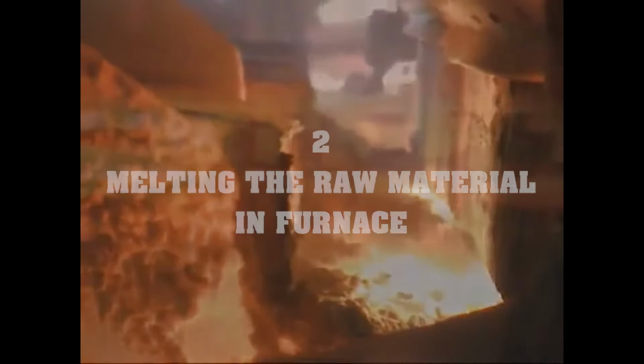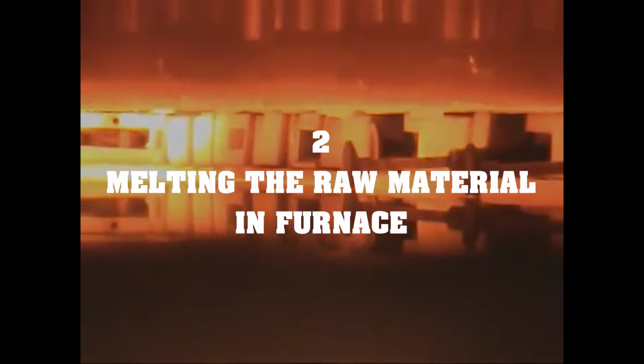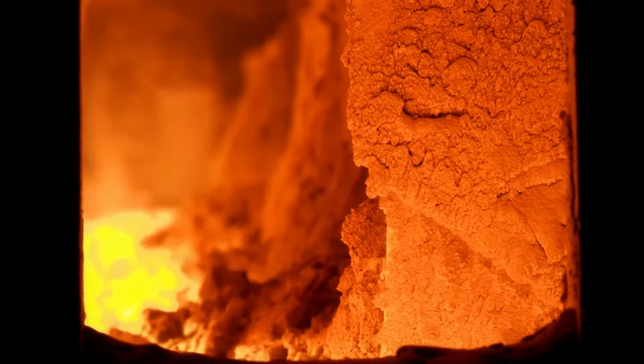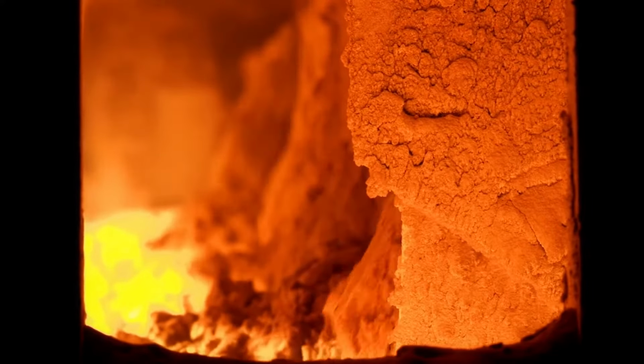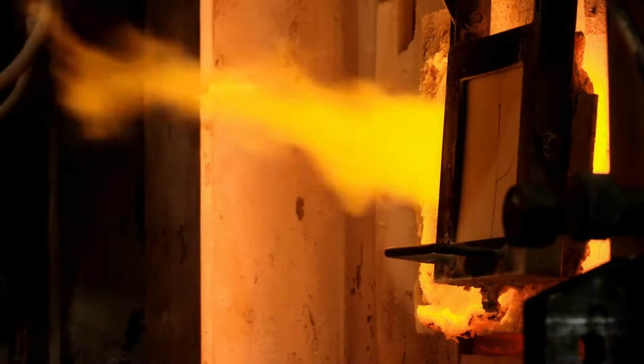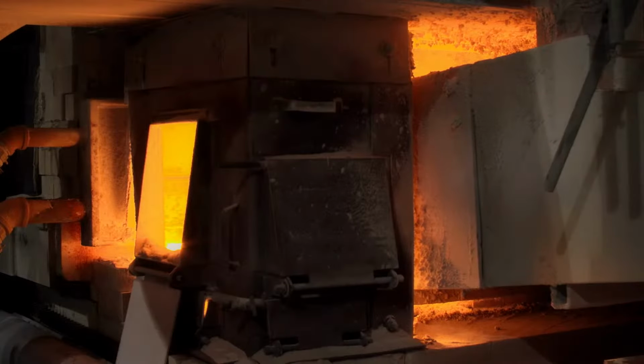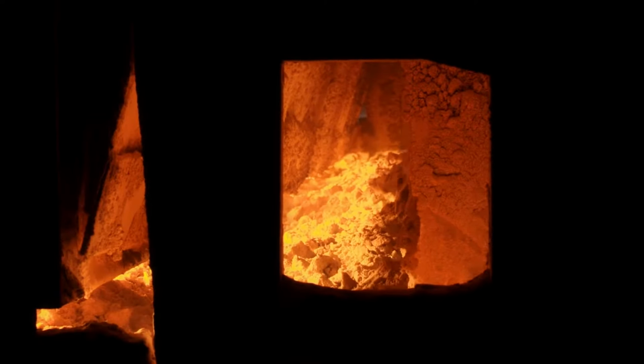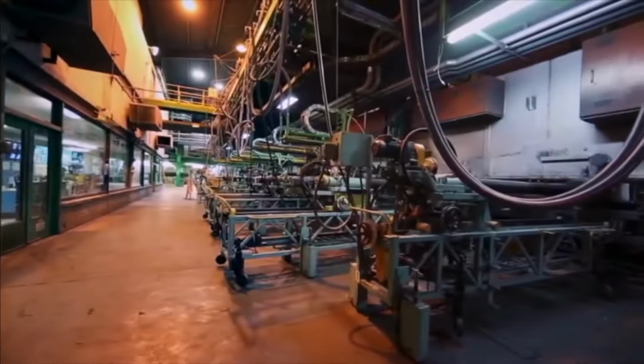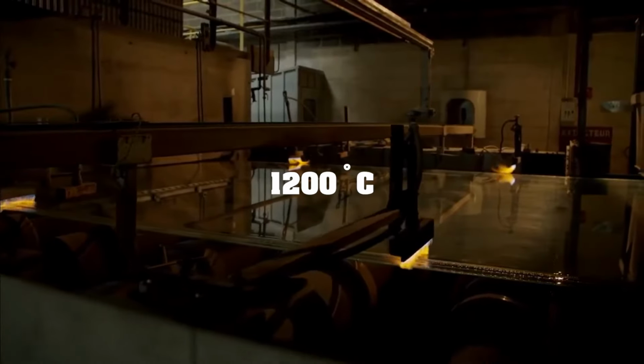2. Melting the raw material in the furnace. The raw material and the cullet are fed into the glass melting furnace. Raw materials by batch are transferred from mixing silos to 5 melting furnaces where they melt. The temperature in the furnace rises to 1600 degrees C. The glass after exiting has a temperature of about 1200 degrees.